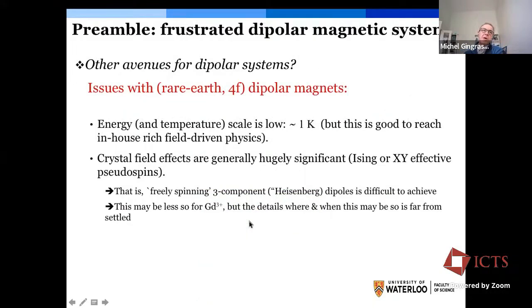So what are the possible other avenues for dipolar systems? Well, while they are interesting, rare earth 4f dipolar magnets have some problems. First and foremost, the energy and temperature scale is low, 1 Kelvin. This is good on one hand because it allows one to reach very rich field-driven physics in house labs. But the problem is that if you want to identify a situation where your dipoles are freely rotating, like the equivalent of a 3-component Heisenberg model, this is very difficult to achieve for rare earths because the crystal field effects will typically be huge, and that will cause the systems to be either Ising-like or XY effective pseudo spins. This may be less the case for gadolinium, but the details of where and when this may occur for gadolinium are not settled.